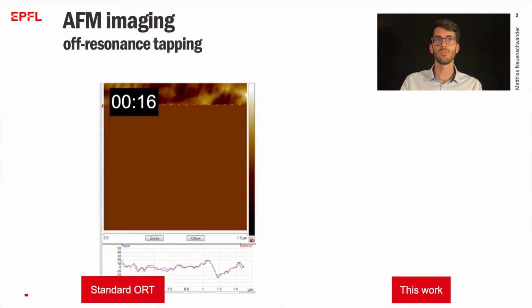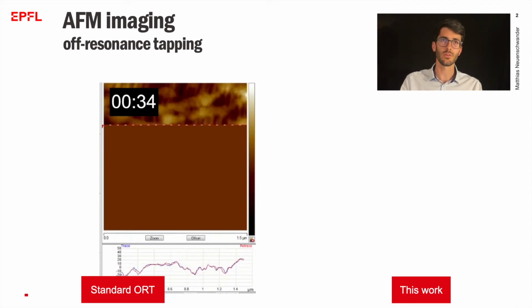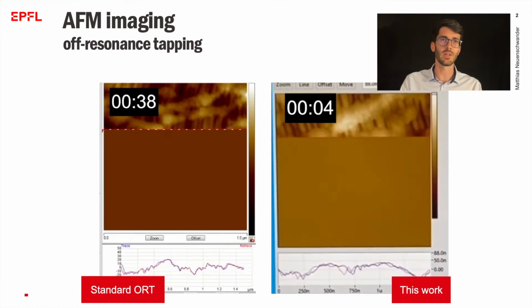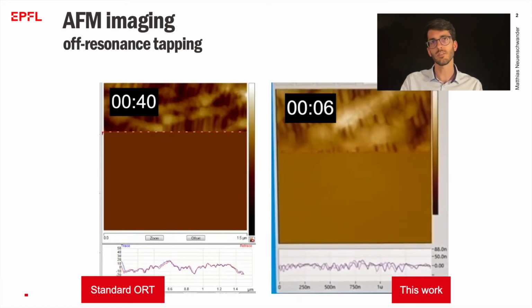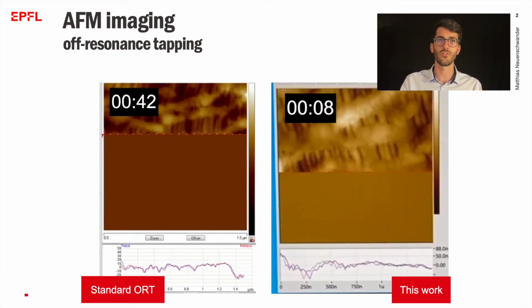Now let me go back to the video I showed you in the beginning. It shows the image acquisition in this off-resonance tapping mode with a commercial cantilever on a Bruker Multimode AFM. Here, each line of the image consists of 500 pixels, and we are obtaining 2000 pixels per second. If we want to obtain at least one force curve per pixel, it follows that we can scan a maximum of 4 lines per second. So it takes a few minutes to get the entire image.